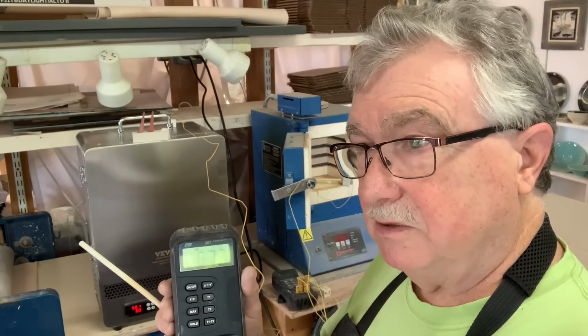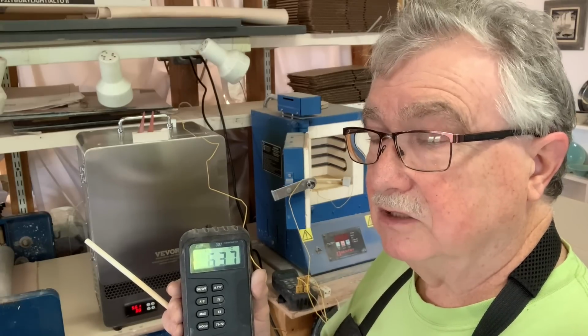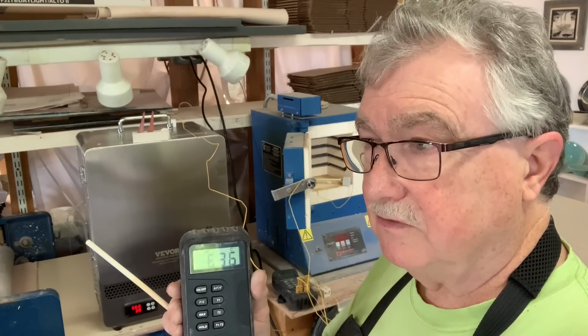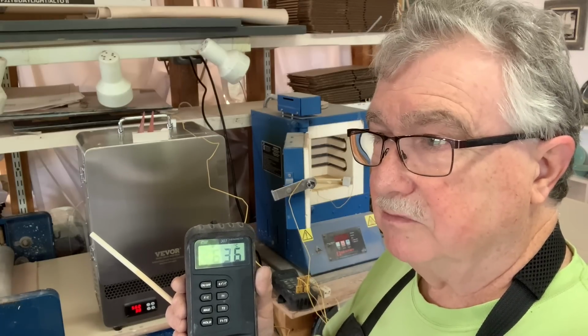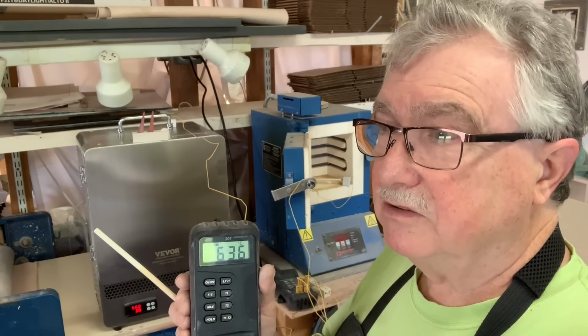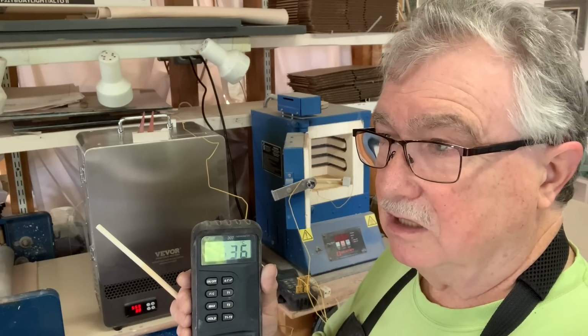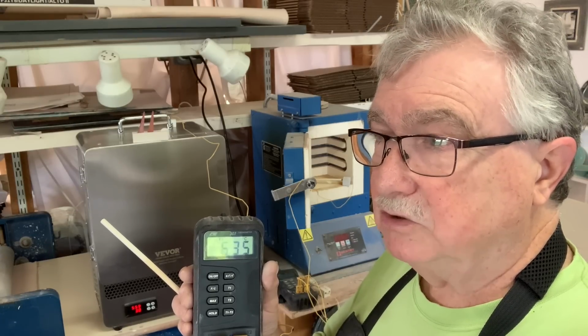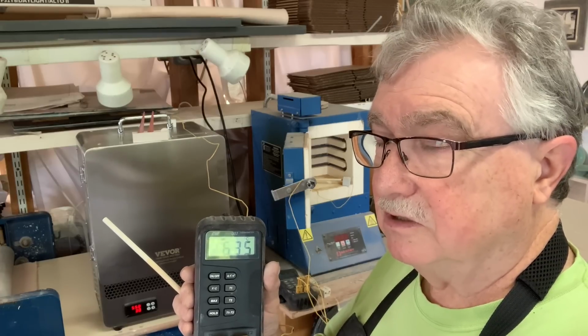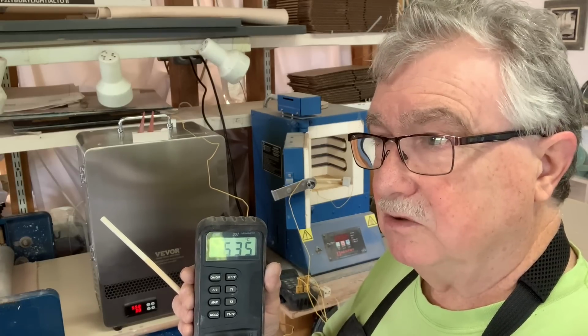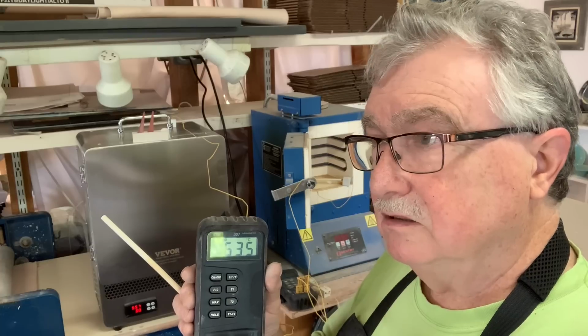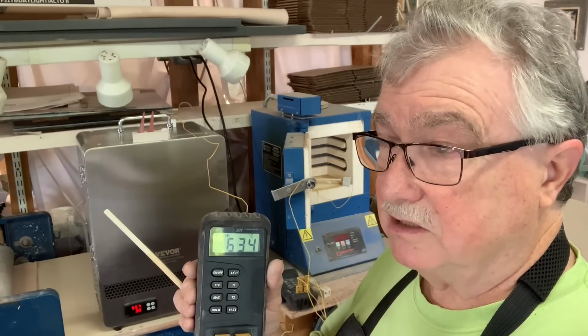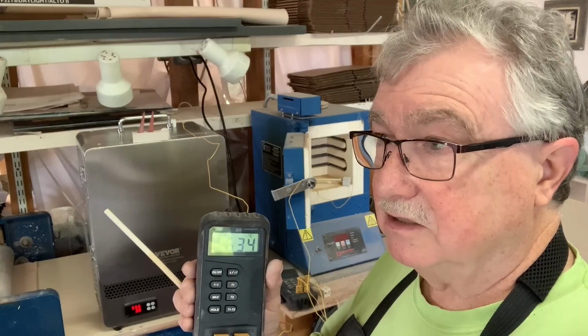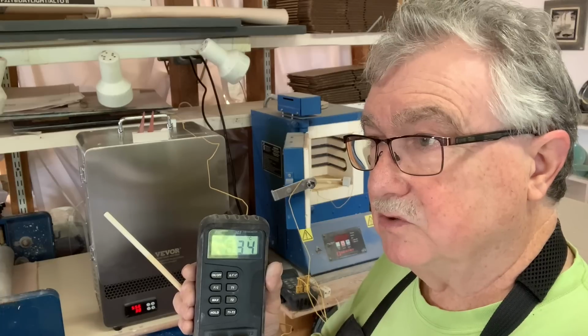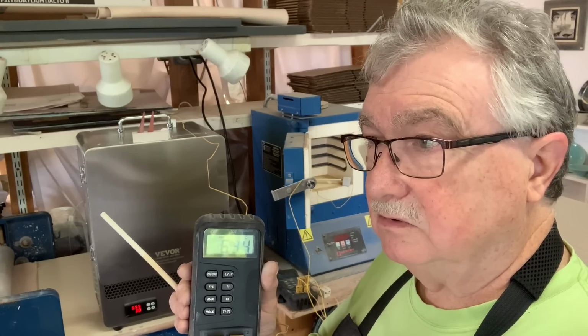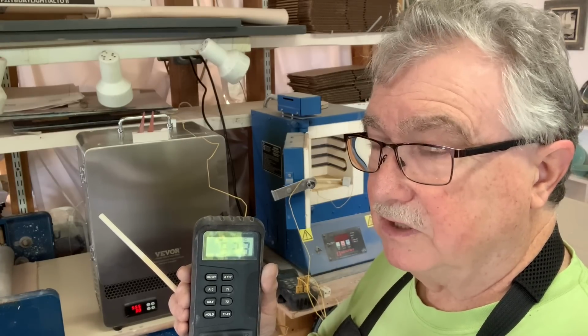It could be that the people who made this kiln know that the actual temperature, because it fires so fast, say in centigrade, well we use Fahrenheit, but centigrade, 1220, cone 6. And in actual fact, in my gas kiln, because it fires a bit slower, and it's a big, huge area, I reach cone 6 at about 1199, which is 21 degrees lower than they say it reaches, but that's centigrade. But if I fire the kiln super fast, it'll be like 1220, 1225, 1230.